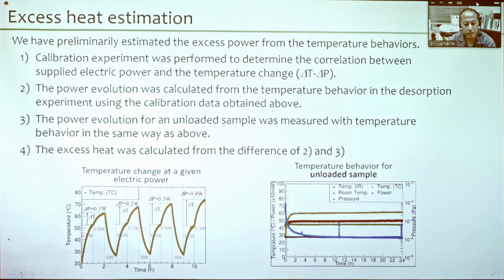Then we consider the behavior for the unloaded sample. So this is the temperature and the pressure behavior for the unloaded sample. So now you may not see a specific change in temperature. I mean, this yellow and red one are the temperature for thermocouple and IR respectively, and you may not see any increase in the temperature. Also, you may not see the pressure increase either. These spikes are the noise of the monitoring system. We have understood that. So the power evolution for this unloaded sample was measured with the temperature behavior in the same way as above. Then the excess heat was calculated from the difference between the desorption experiment and the unloaded sample experiment.